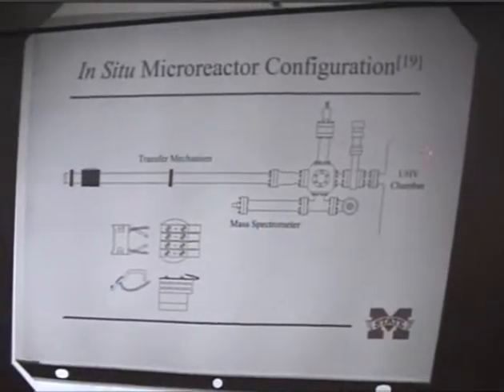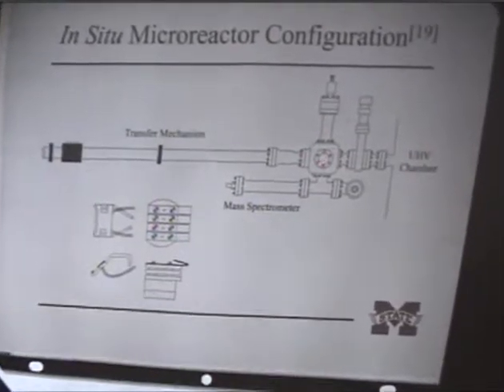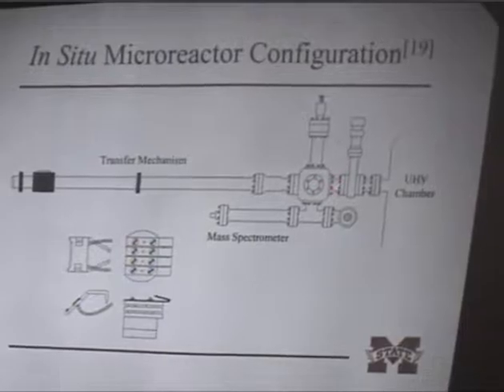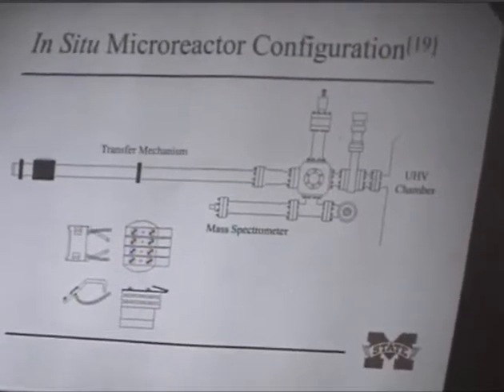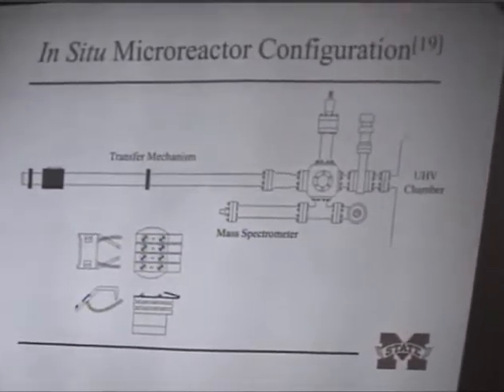Now the problem is that this is an ultra-high vacuum, so if you talk about a realistic model, we're at 10 to the minus 10 torr, which is orders of magnitude away from anything you would see in a car. So what we decided to do then was we needed to expose the sample to SO2 under more realistic types of conditions. And so we built this microreactor, and the only important thing I'd like to point out is we had a mass spectrometer hooked up to it. All the experiments we did were in a batch mode. We would like to do it in a continuous mode next, and that's one of the things we're going to